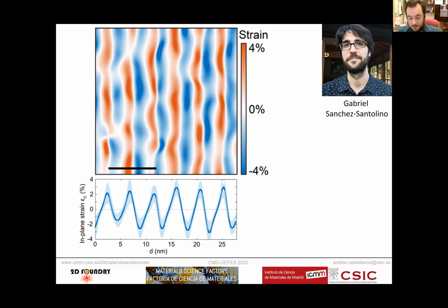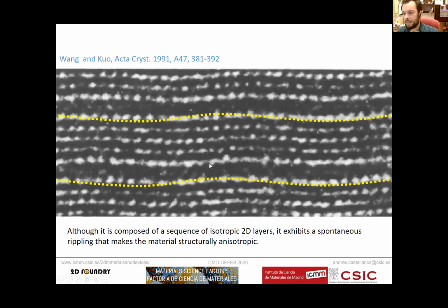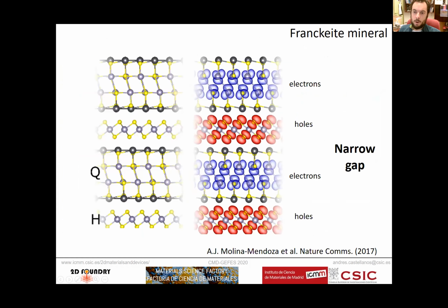Since we started working on this Franckeite, we've always been wondering how to get insight into whether there is a preferential top layer or not. It could happen that, if the material is completely stable, whenever you exfoliate you get a 50% chance of the tetragonal and a 50% chance of the hexagonal layers. But it can also happen that whenever you expose one of them to air, it degrades, and then you get a preference for one layer. Those are the two scenarios, but we do not have the right tools to test them. We are still working on it. It's an open question so far.